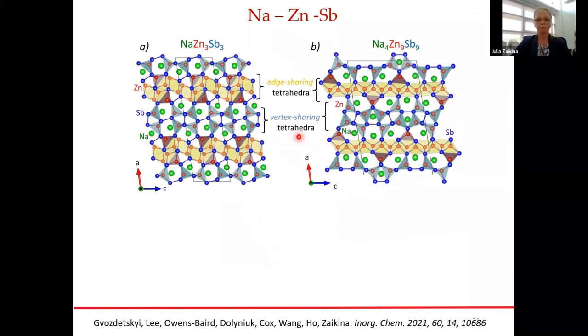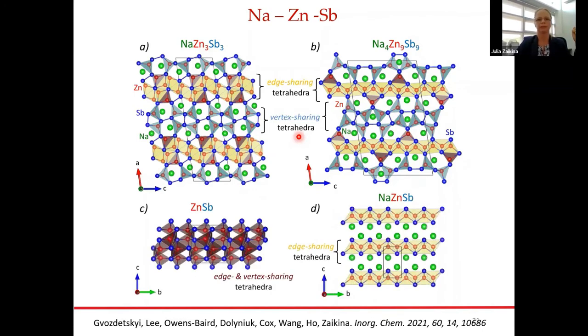And so those phases are very structurally complex, but they still have fragments from that binary, as well as this ternary 1,1,1 phase. So for instance, here highlighted in yellow, you can see this edge-sharing tetrahedra of zinc with antimony in the corners. And this fragment is present in the 499 phase, as well as in the 133 phases. However, the structural complexity of those 2 phases is achieved by inserting vertex-sharing tetrahedra, as well as the presence of these edge and vertex-sharing tetrahedra units. And so this gives a very complex zinc antimony framework with sodium cations filling the space within, like, the channels of that framework.